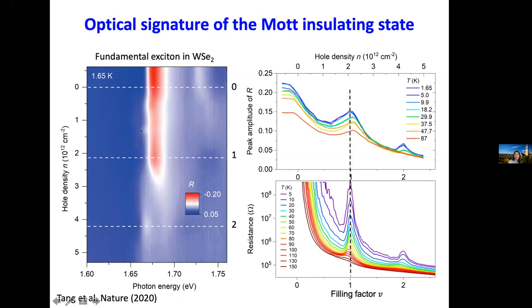But if you have a good imagination or sharp eye, if you look at the counterpart more carefully, you see, okay, it looks like here and here, you also have kind of an enhancement of the exciton absorption. And this probably also tells you that your sample is in some kind of an insulating state because the electron-hole interaction is strong at those fillings.